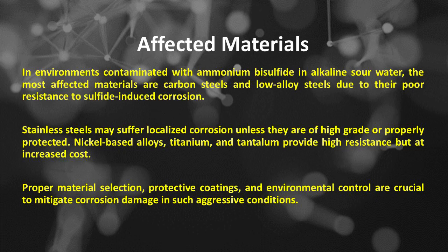In environments contaminated with ammonium bisulfide and alkaline sour water, the most affected materials are carbon steels and low-alloy steels due to their poor resistance to sulfide-induced corrosion. Stainless steels may suffer localized corrosion unless they are of high grade or properly protected. Nickel-based alloys, titanium, and tantalum provide high resistance but at increased cost. Proper material selection, protective coatings, and environmental control are crucial to mitigate corrosion damage in such aggressive conditions.